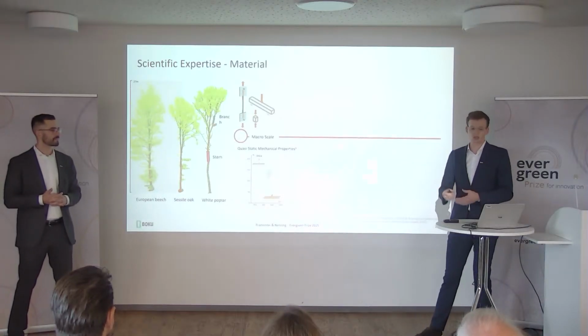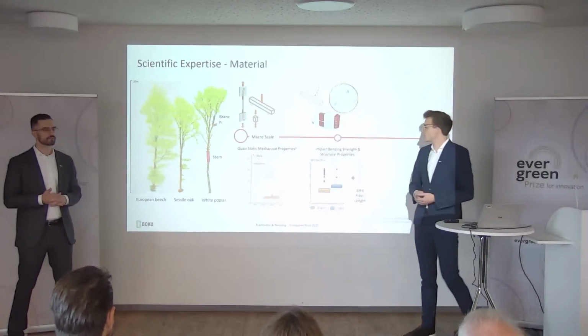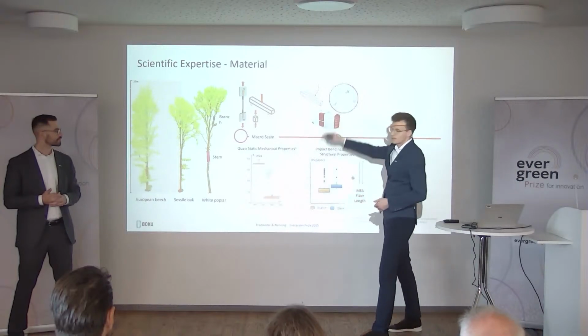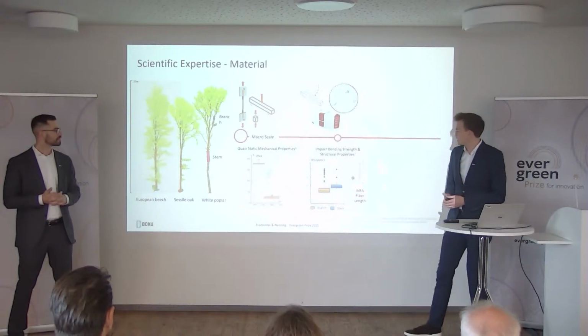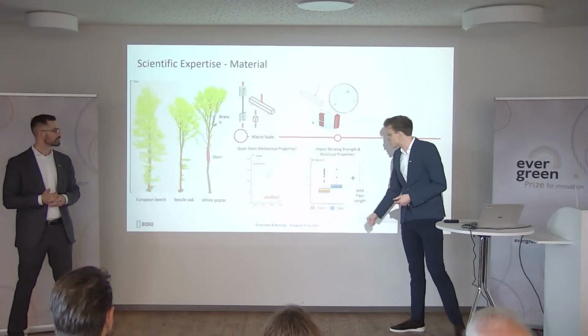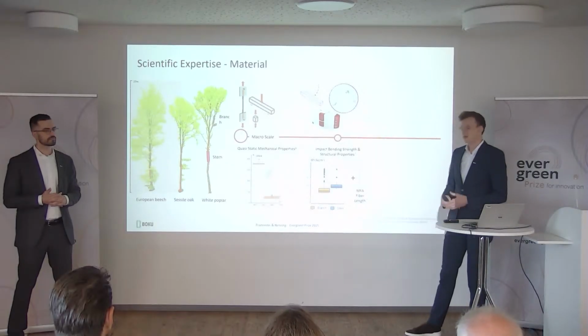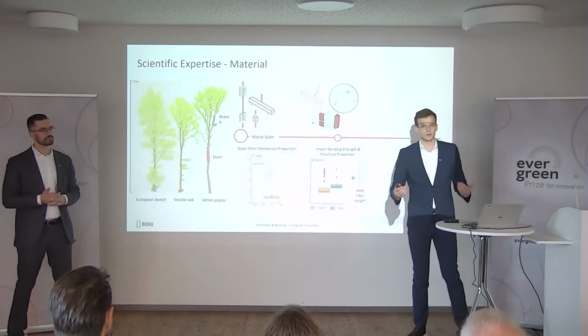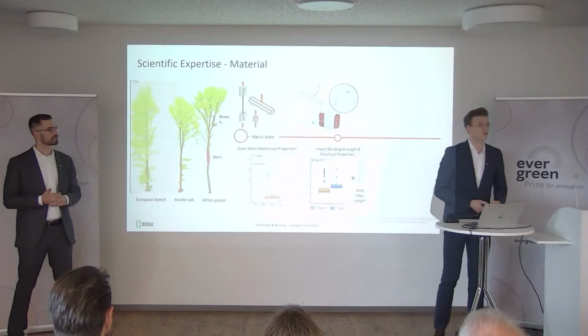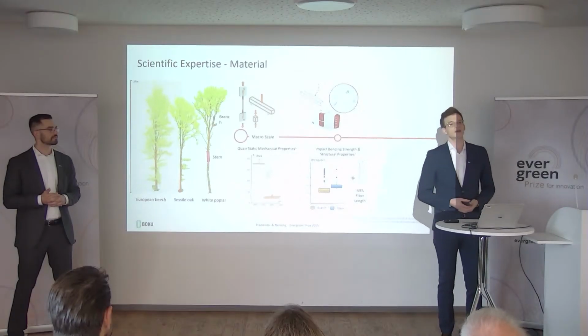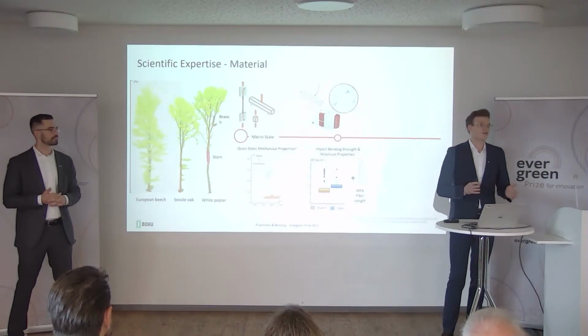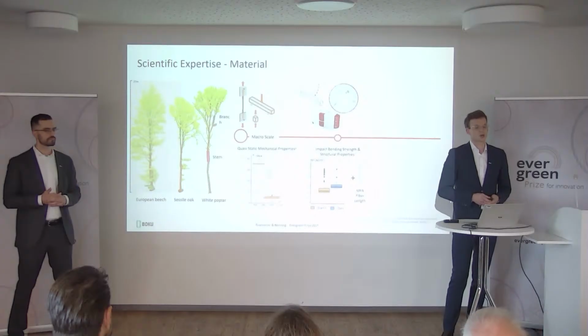When it comes to a resource-efficient use. We looked one level deeper, impact bending strength this time, and we again found out branchwood does actually have a lower impact bending strength than stem wood. So what could be possible reasons? We looked into fiber length, for example, and we found out the fiber length of branchwood is around 25% lower than the one in stem wood.